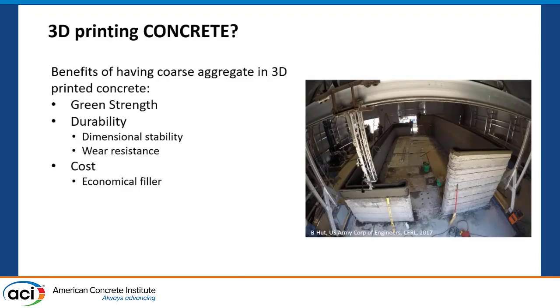There is some benefit to actually having coarse aggregate in your 3D printable concrete because green strength — the early age strength — is higher. Long term, you have better durability. 3D printing is typically done with cement paste or cement mortar, but having coarse aggregate gives you better durability, better dimensional stability, and shrinkage resistance. Most importantly for cost, you have a cheap volumetric filler in aggregates instead of cement paste, which can make this an expensive material.